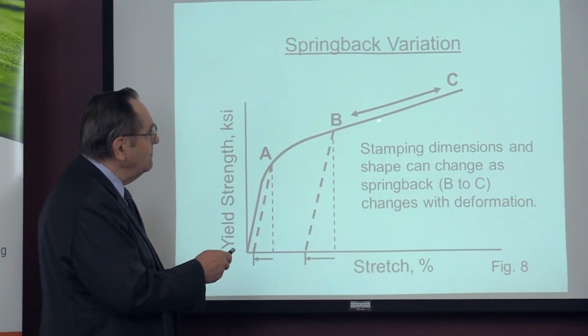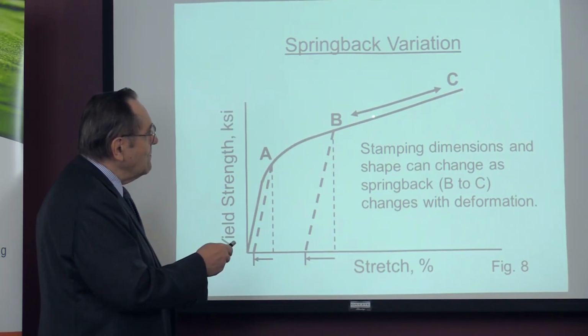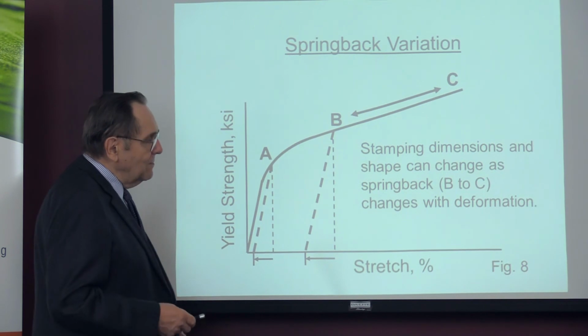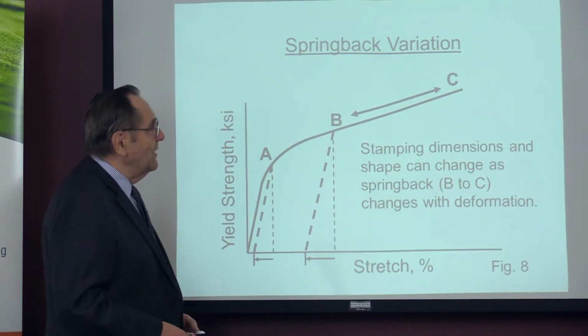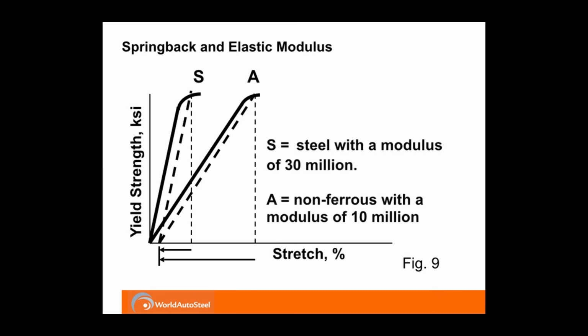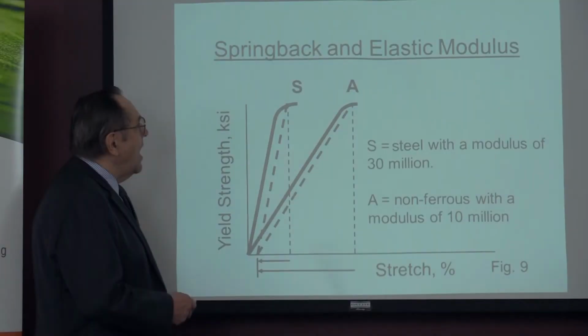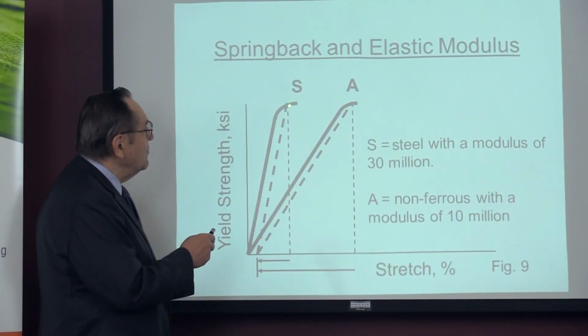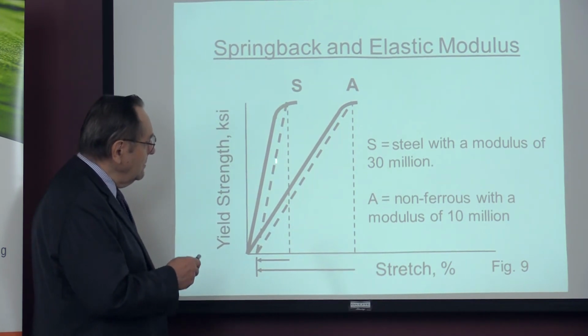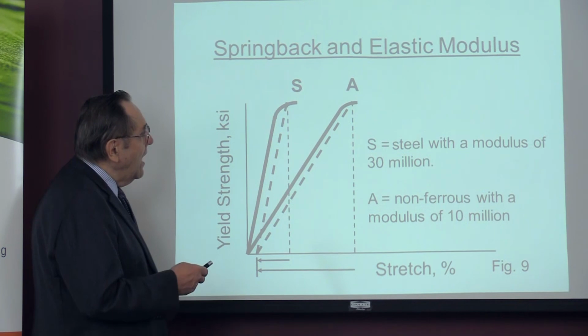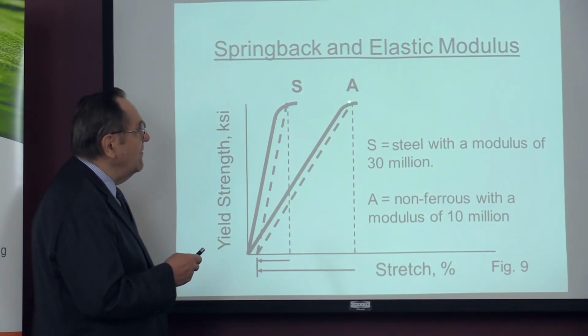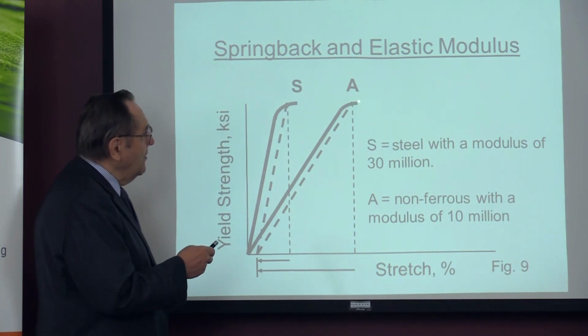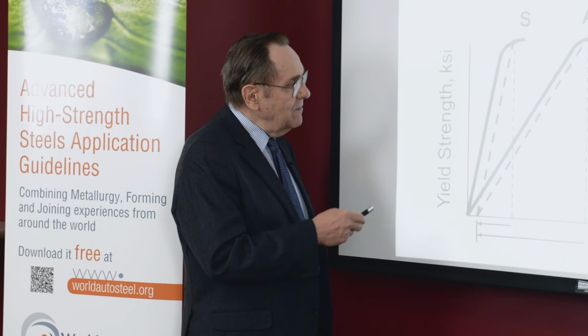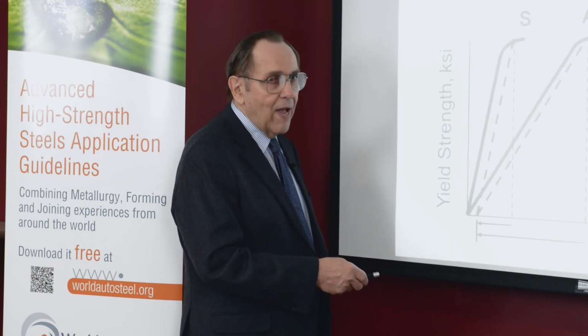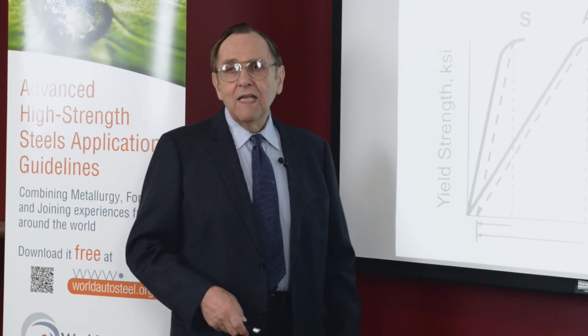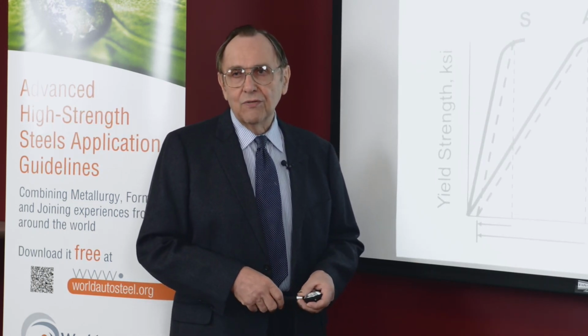So now we have this from it, and you can see why this springback is a real problem now because of these elastic stresses, which we can't measure and we can't see. Well, it even depends upon the modulus of elasticity. For steel, we have a 30 million modulus, and we have this amount of springback. For aluminum or a non-ferrous metal, which is 1/3 the modulus at 10 million, has now 3 times the amount of springback. And so the springback depends even on what material you are going to use.